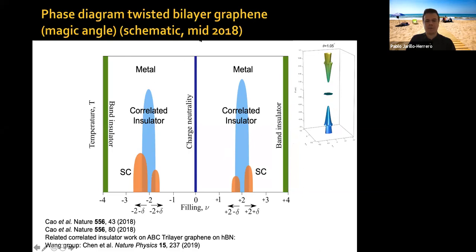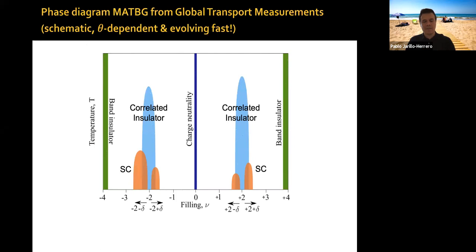So if you go to magic angle graphene, this is the phase diagram, again, schematic. This was the phase diagram in the summer of 2018. You have this correlated insulator behavior when you put two electrons, two holes per moire unit cell, and you have superconducting domes around them. When you dope a little bit, remove your filling factor a little bit away from two holes initially, then it was discovered that it also happens on this side, and then many other domes were seen. And I should mention that related correlated insulator work on ABC trilayer graphene aligned to hexagonal boron nitride was published at about the same time by Feng Wang's group and collaborators at Berkeley. So this field evolved very quickly. From global transport measurements alone, this phase diagram is evolving very fast. And it's extremely twist angle dependent, and also it depends on other parameters. So this is what I told you about the summer of 2018.